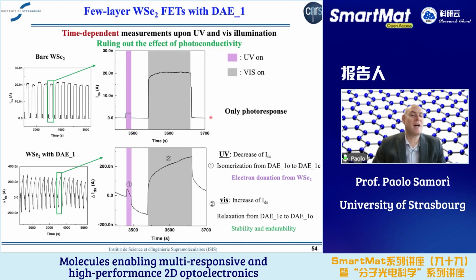And of course, when you start irradiating a semiconductor with light at different wavelengths, you can wonder whether the effect of this change in the current was due to a photoconductivity effect. And so to rule out the photoconductivity, we took the bare tungsten diselenide and we did the same experiment. You can see that when we irradiate with UV light and when we irradiate with visible light, in both cases, in the bare tungsten diselenide, we have an increase in the current.